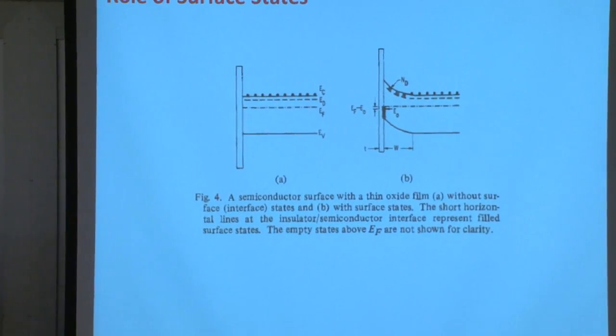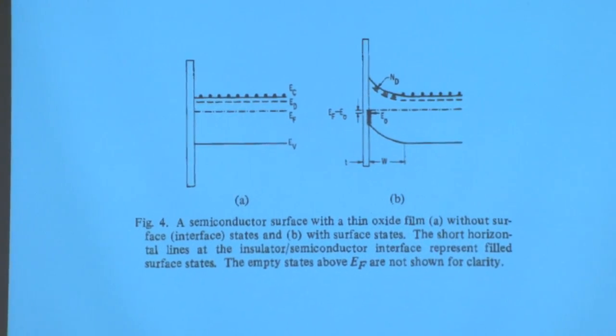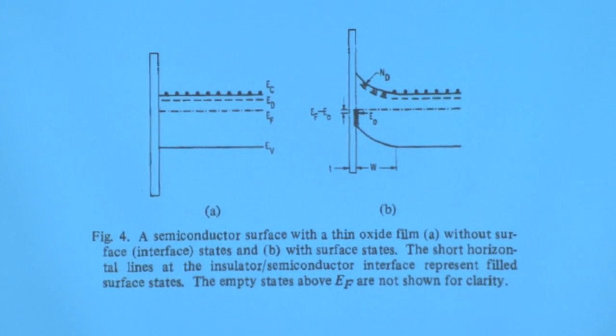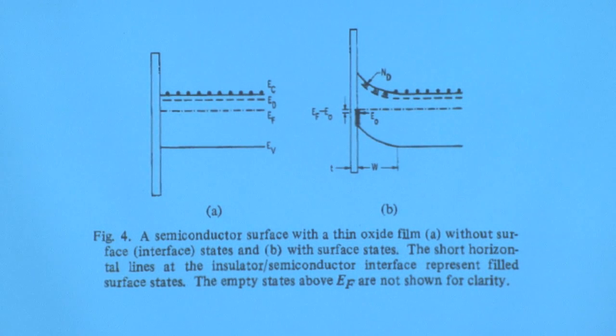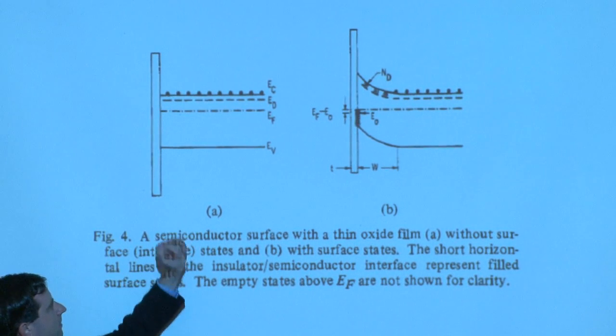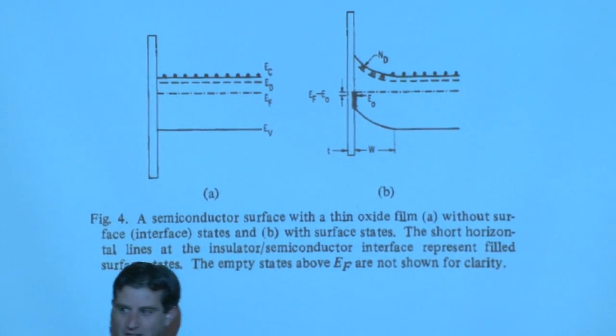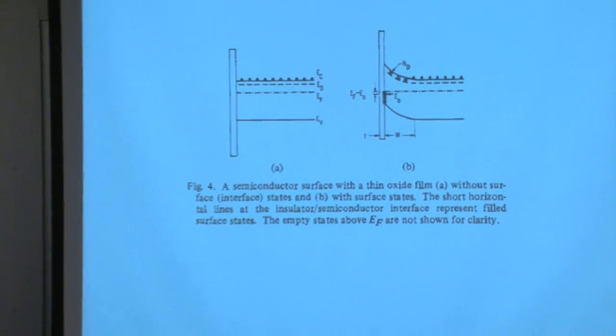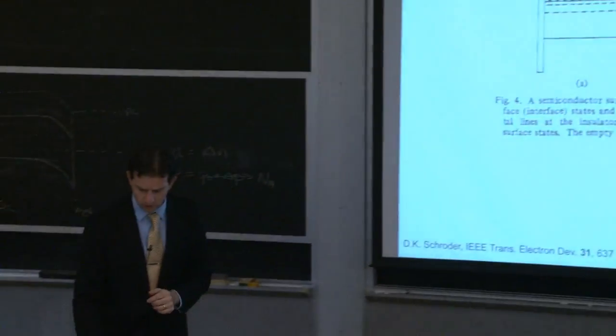If you have a metal or say a semiconducting oxide forming at the surface, or if you happen to be exposing it to a sulfur-based gas right after you grow it, and you form some sulfide at the surface, the surface chemistry is very important for dictating the band bending at the surface. Why is that important? That's important because when you go ahead and deposit a metal on top of it, now you not only have to contend with what the semiconductor is doing, but what that semiconductor surface layer is doing. Right? Now the situation is really becoming complex.